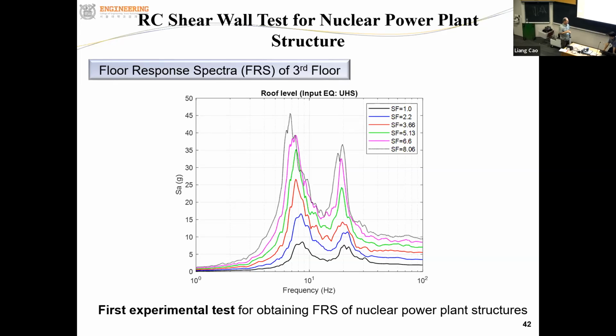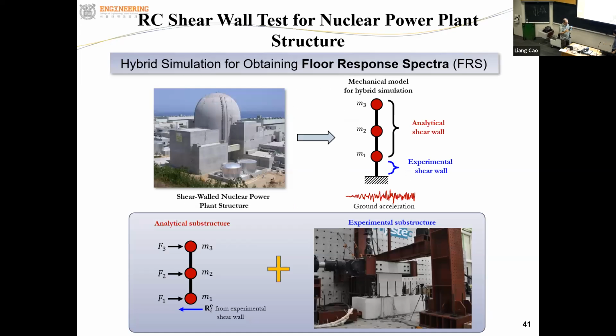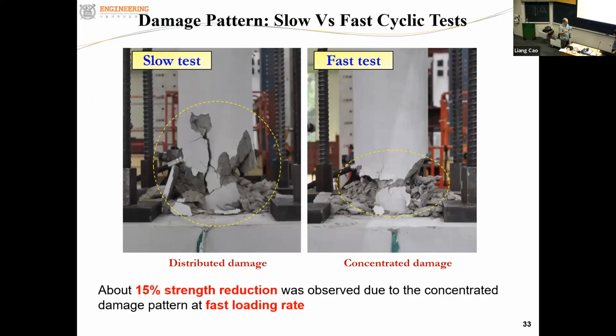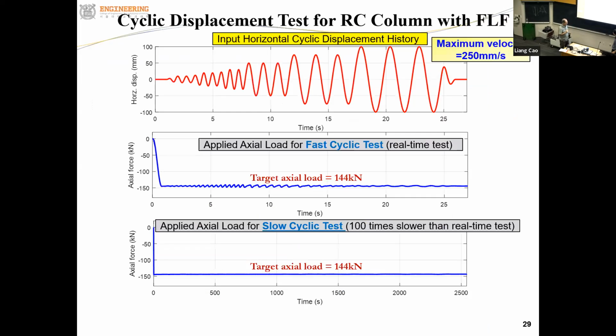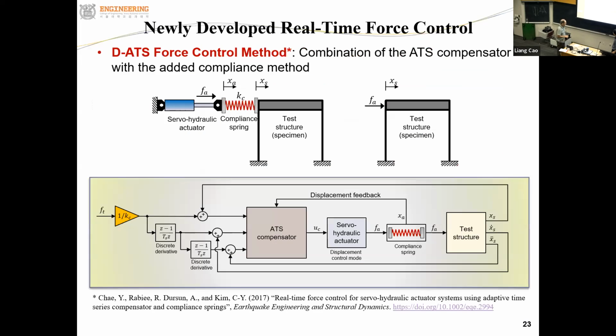I have a question. The compliance there is also going to be influenced by the compliance of the test specimen itself, especially axially. These specimens are very rigid, very low compliance. What happens if you have ones with more coupling, that is, more compliance in the test specimen? The axial force would probably still be more challenging, because the deformation in the spring will develop a force, but it will also rely on the deformation of the specimen, either in series or in parallel, right?